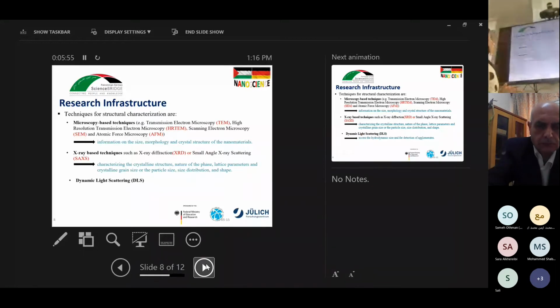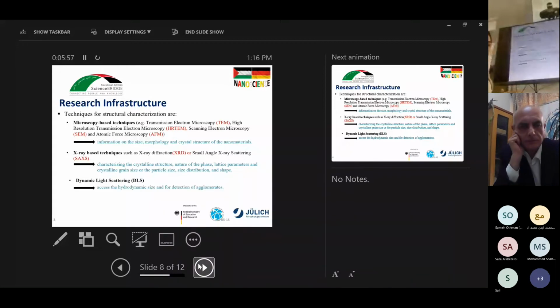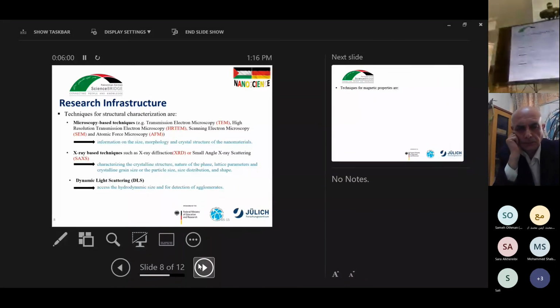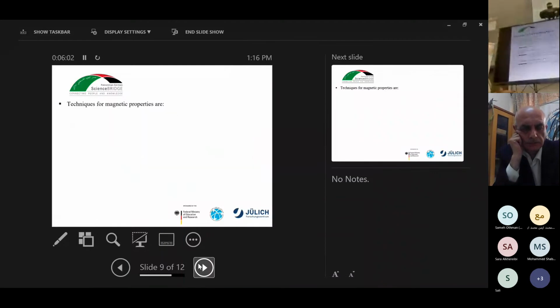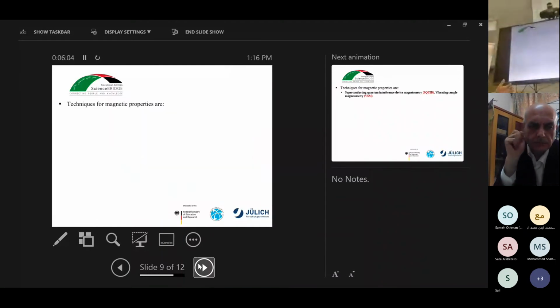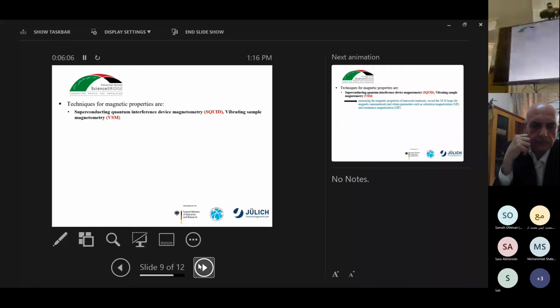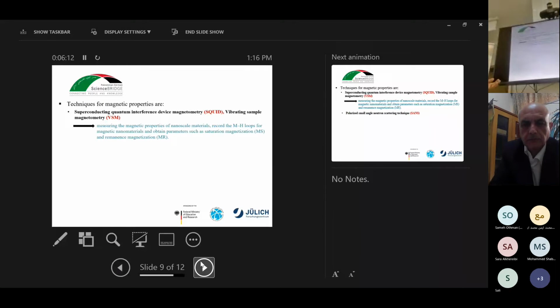Also, they need dynamic light scattering measurement in order to assess the hydrodynamic size and for the detection of agglomerates. Furthermore, for the magnetic properties they need the superconducting quantum interference device, SQUID, magnetometry, and vibrating sample magnetometry. By using these techniques, they aim to measure the magnetic properties of the nanoscale material, record the magnetization versus field loops for the magnetic nanomaterial, and obtain parameters such as saturation magnetization and remanence magnetization for their system.